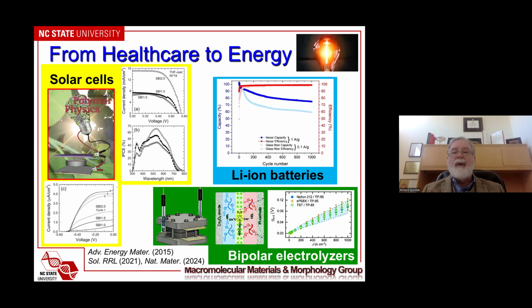Lastly, we can make bipolar electrolyzers. And in this case, yes, we need to have a catalyst. And so the catalyst that was designed here was a tin oxide catalyst, but it was only 3 nanometers in diameter. So it had a very, very high concentration of surface atoms. And what we found was if you look at the overvoltage as a function of current, our results from this polymer, which is shown here as TST, were on par with Nafion. And it's important to realize Nafion is fluorinated. So it has that negative connotation with it. Our material is non-fluorinated. So it's a safer material to use as well. And it's a lot less expensive than Nafion.